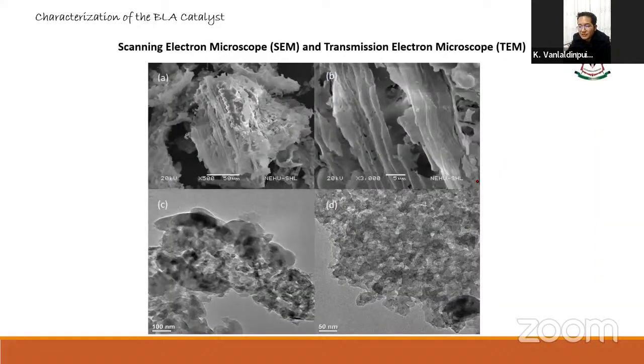Then we used SEM and TEM analysis to study the morphology of the catalyst. A and B are SEM images, which reveal the spongy nature of the catalyst. C and D are TEM images, and they show different size distributions of the catalyst, with diameters ranging from 10 to 30 nanometer.